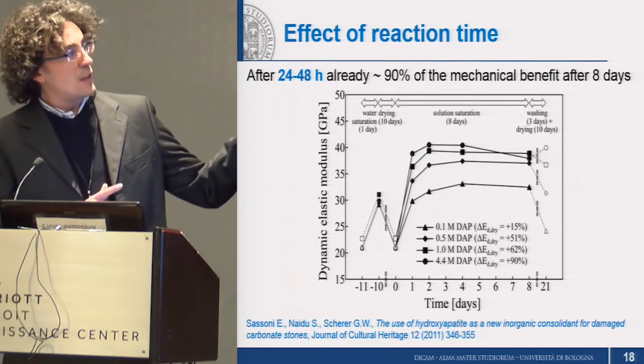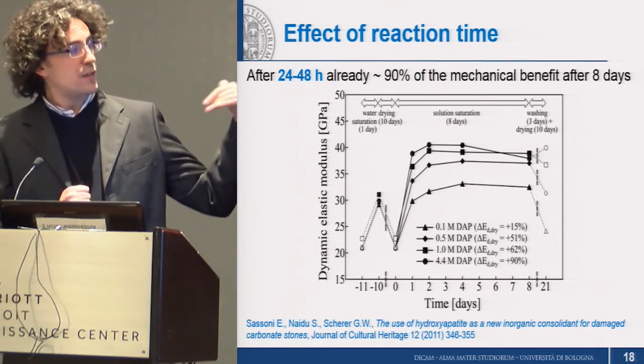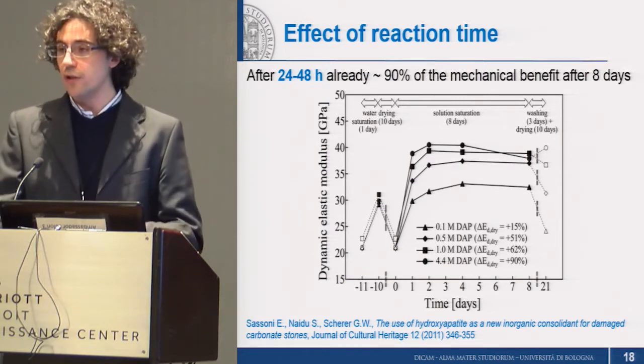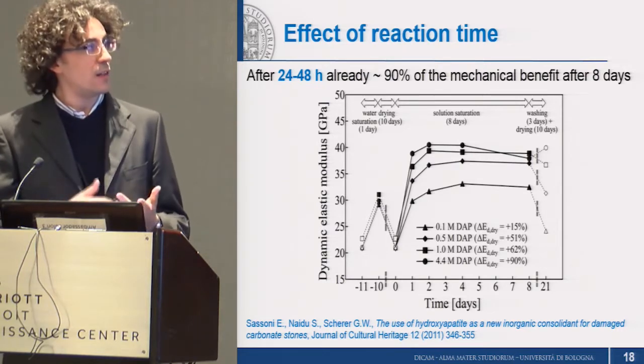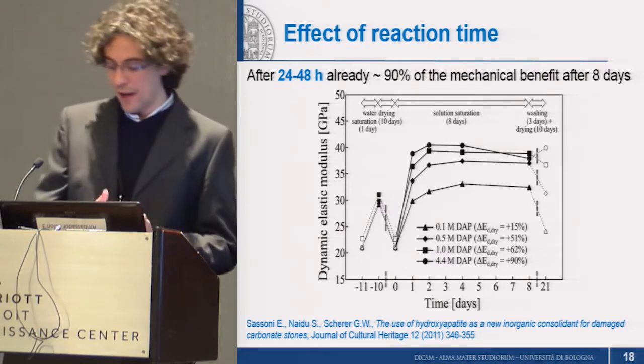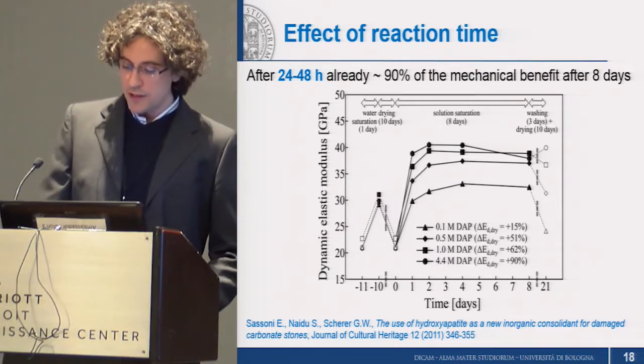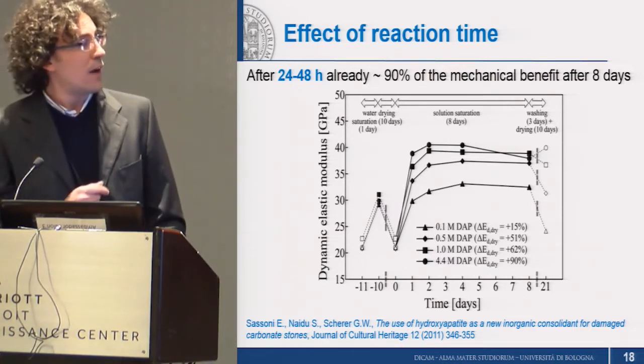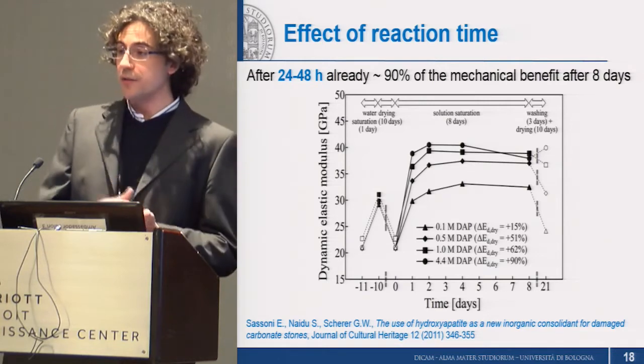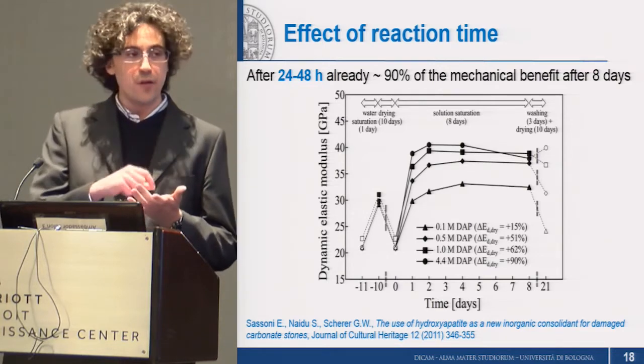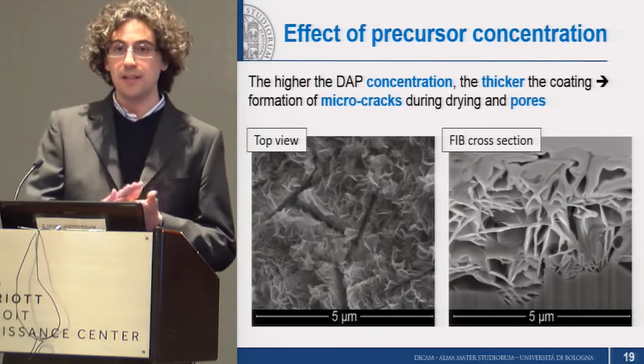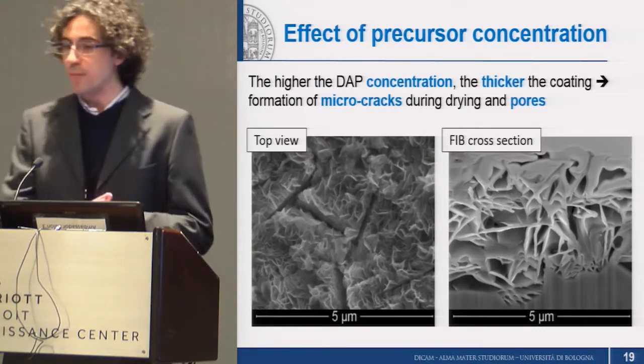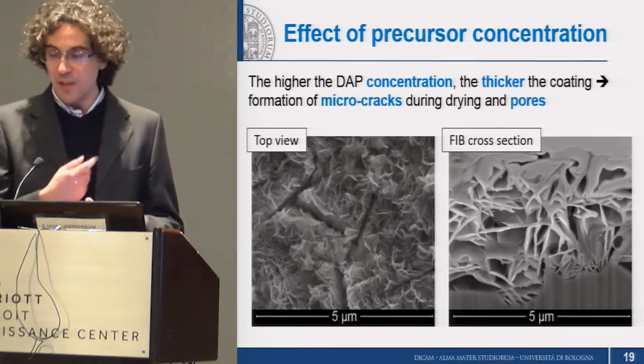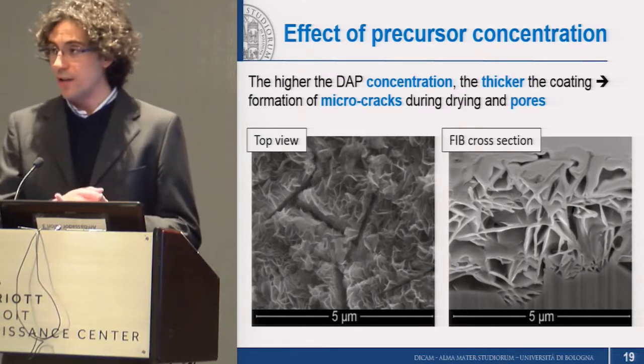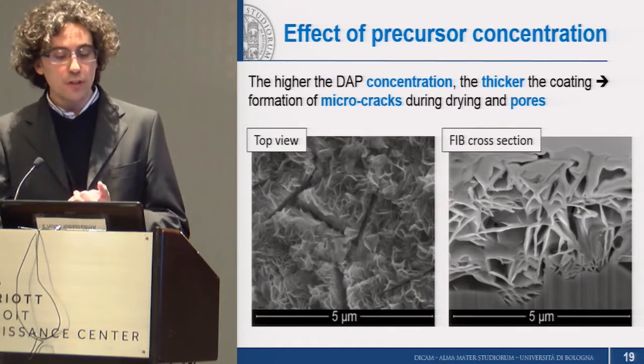Here you can also see the influence of the precursor concentration. So generally speaking, the higher the concentration, the higher the consolidating effect that we get. However, the higher the concentration, the thicker the layer that forms on top of calcite, and this is potentially a problem because a higher thickness may lead to cracking during drying of the coating.